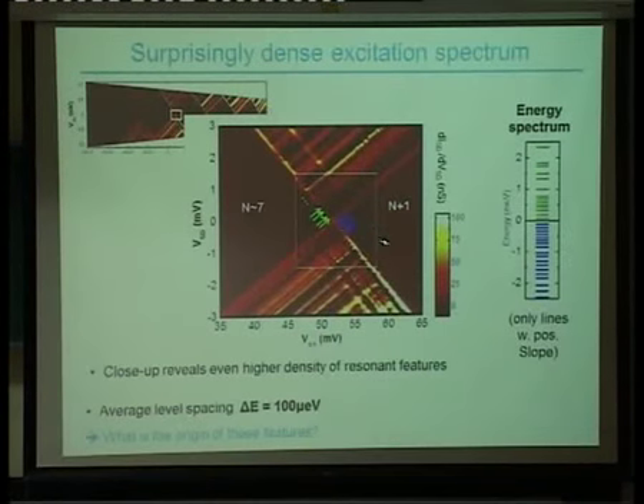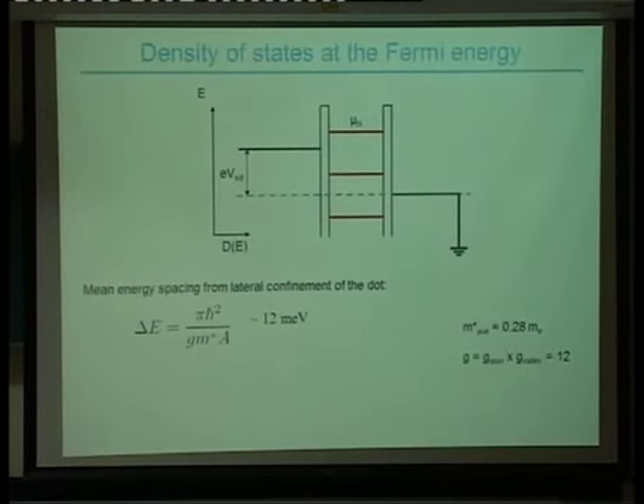If you zoom in, you can see these resonances are separated by about 100 microeV. So I guess this was really unexpected. We've made this very small quantum dot structure. And you would know that as you make things smaller and smaller, the quantum energy levels should be further and further apart. But we're finding that we get these energy levels that are incredibly close together. So you can look at the mean energy spacing that you would expect just from the physical size of the dot. And you can work out that that should be about 12 millielectron volts.